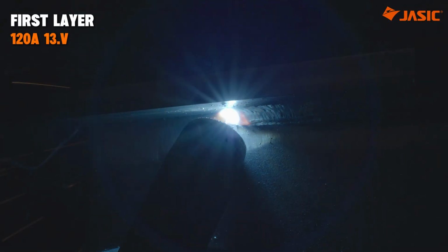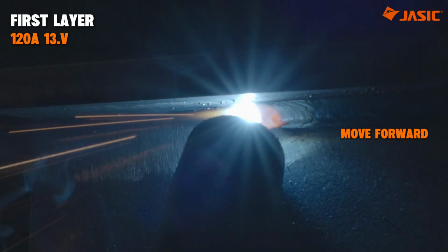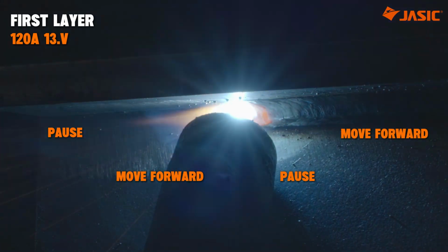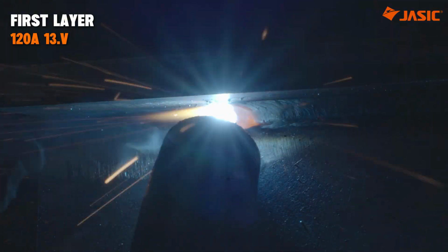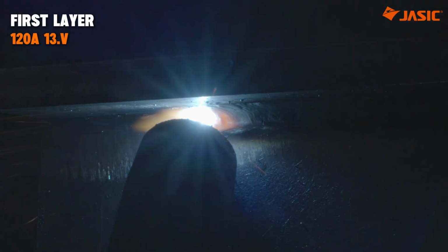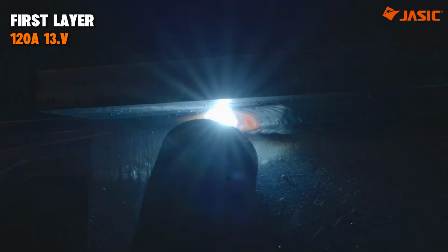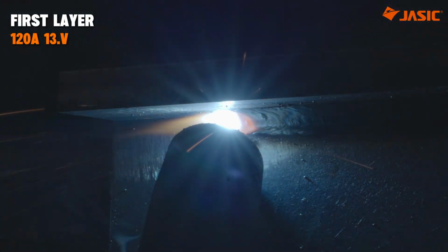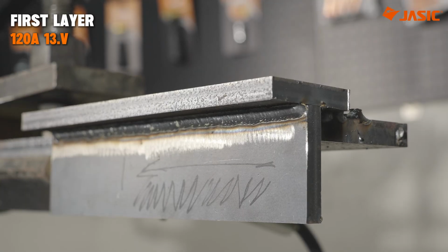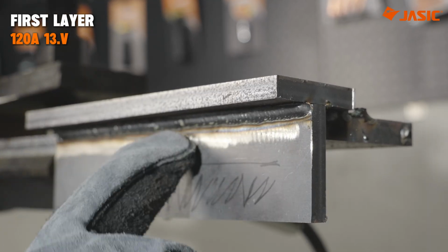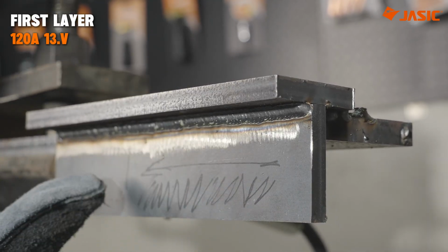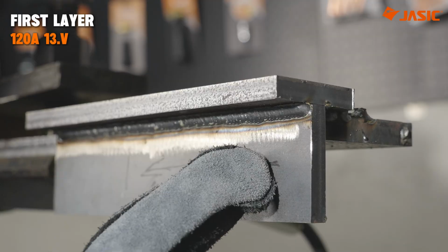First layer, straight travel for the root pass: move forward, pause, move forward, pause. Don't drag the gun continuously. Move forward a short distance, then pause briefly to let the molten pool fill the joint and fuse properly with the base metal. This creates a compact, well-formed root pass and gives you a solid foundation for the second layer. After finishing the first layer, don't immediately start the second one.